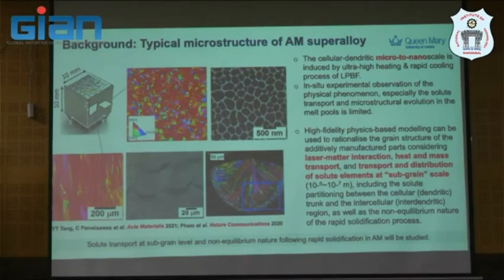And the in situ observation of this phenomenon, especially solute transport and microstructural evolution, is very limited. I would say almost none, because the resolution required is quite small. And high fidelity simulation will be relevant to rationalize what happened in terms of laser matter interaction, heat and mass transport, and at the subgrain scale. We're talking about the 10⁻⁶ meter, or about 100 nanometer scale. This solute partitioning between the cellular or dendritic trunk and the intercellular or interdendritic region will contribute to the non-equilibrium rapid solidification nature.